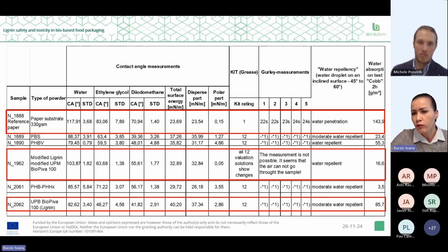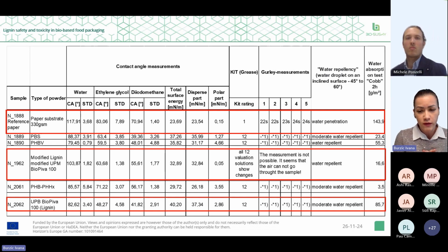From those results on water repellency and kit rating, we can see that once UPM BioPIVA lignin was not modified, it showed some moderate water repellency, which was the same for the PHBH thermoplastic polymer. But once lignin was modified, we observed water repellency, which is our target here. It's a bit different, quite different, once we look at the grease resistance.